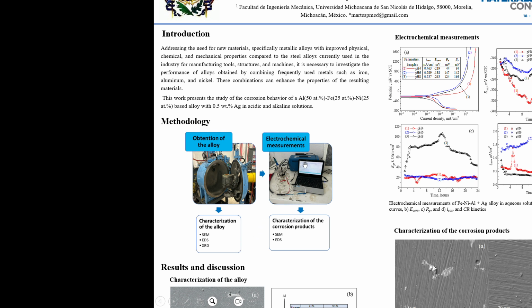The electrochemical cell was set up with 3 electrodes, a calomel standard electrode, a graphite bar, and the alloy as reference, auxiliary, and working electrodes, respectively. The solutions were prepared with water, hydrochloric acid, and sodium hydroxide to reach pH values of 4, 6, and 8. On the one hand, potentiodynamic polarization tests were conducted by applying a polarization potential range from minus 500 to plus 1500 millivolts versus the open circuit potential with a scanning rate of 1 millivolt per second.